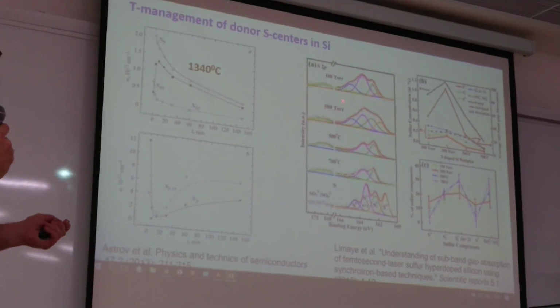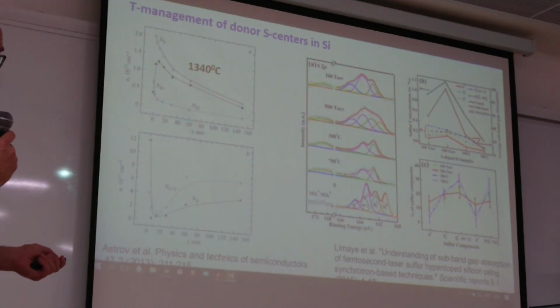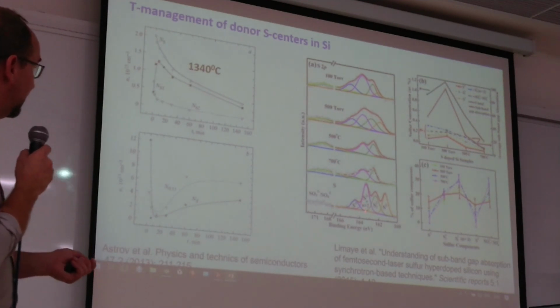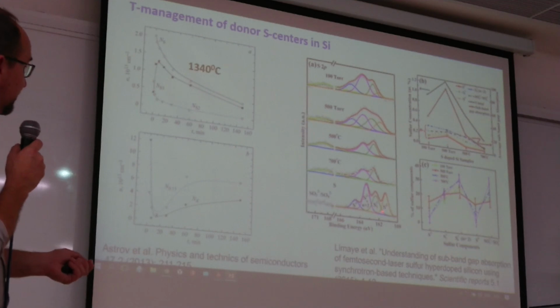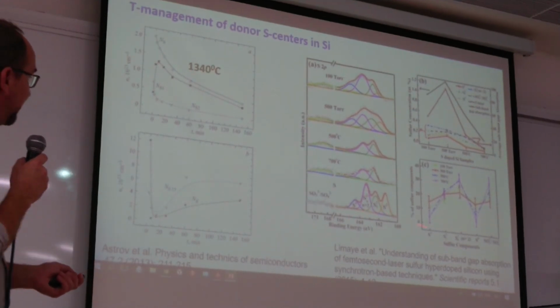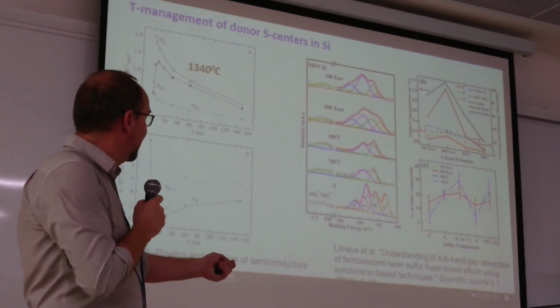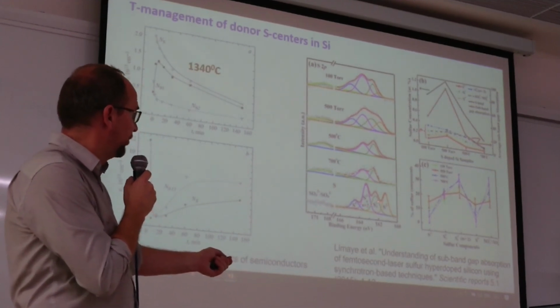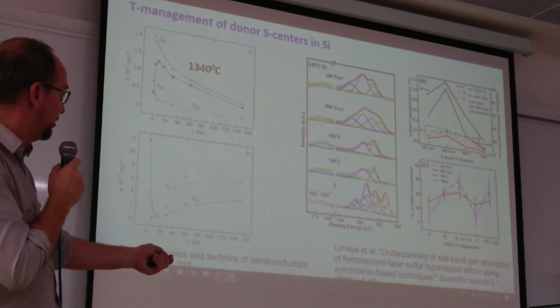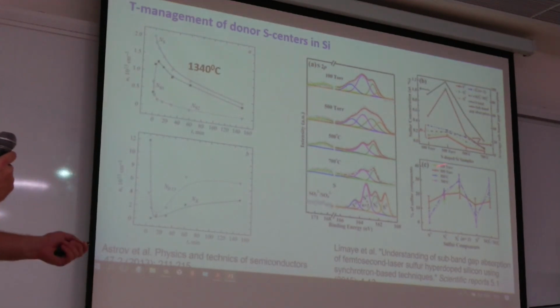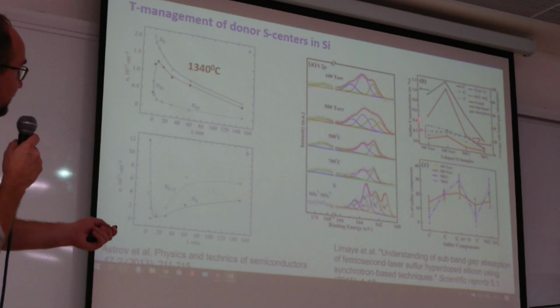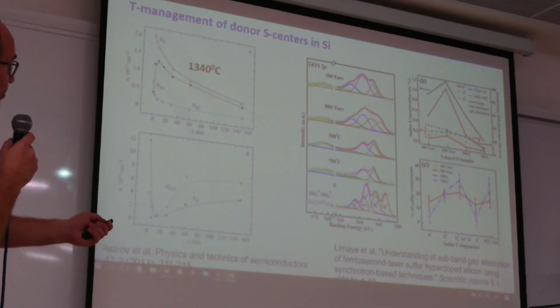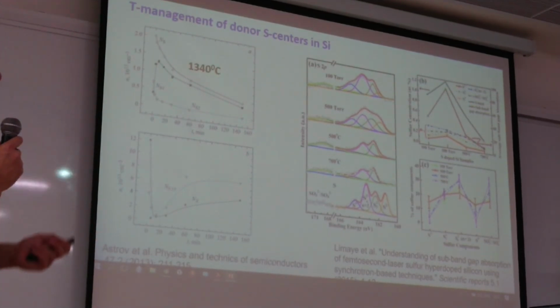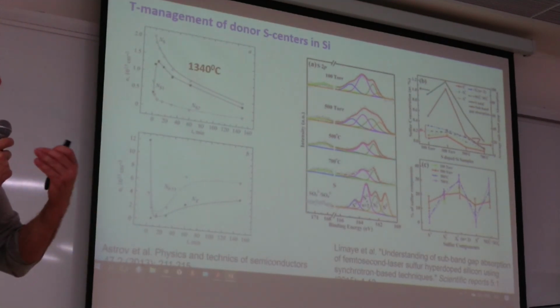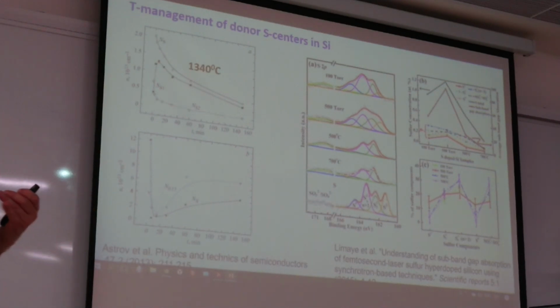They have found in XPS spectra a number of components corresponding to atomic sulfur, charged sulfur, diatomics and aggregates, sulfur aggregates, which are called Sn, where the number of atoms is more than 2. So these are diatomics, these are charged atoms, and this is neutral atoms. So these components can be considered as a function of pressure and temperature, and there are minima and maxima, so there are optimal conditions for each center. It looks like increasing temperature makes the aggregation of sulfur atoms in silicon more advantageous, and this can be used for other purposes.